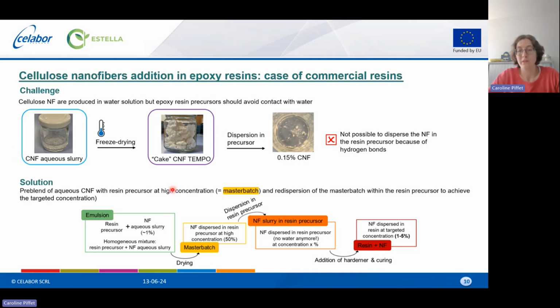and then redisperse this master batch into the resin precursor to achieve the target concentration. So first we prepared an emulsion between the aqueous dispersion of nanofibers and the resin precursor. This is homogeneously mixed with limited time of the resin precursor in contact with water to avoid degradation. We dry this emulsion to obtain the nanofibers dispersed at a ratio of 50% into the precursor.